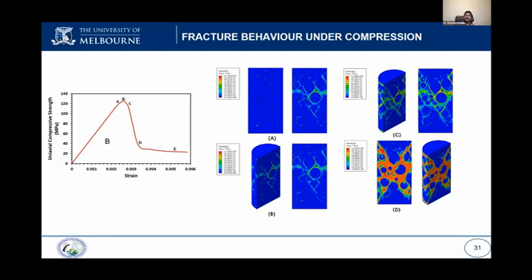But we can't see what's happening inside, what's happening in ITZ, because ITZ is like 2, 3, 4 micrometers in depth. It has a thickness. So we can't get the result from ITZ when we are testing it. But using the FEM simulations, mesoscale simulation, we were able to unlock and find the failure mechanism in the concrete. So what we found, this A is related to the damage in ITZ.